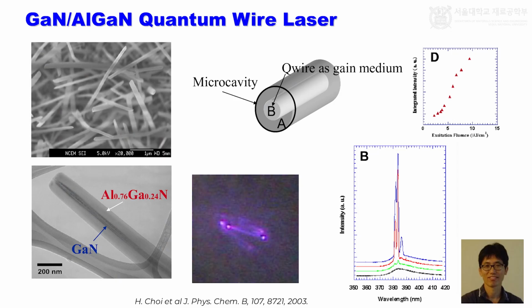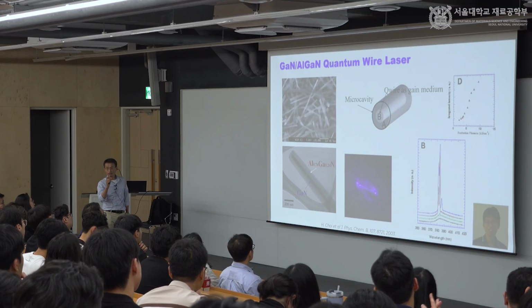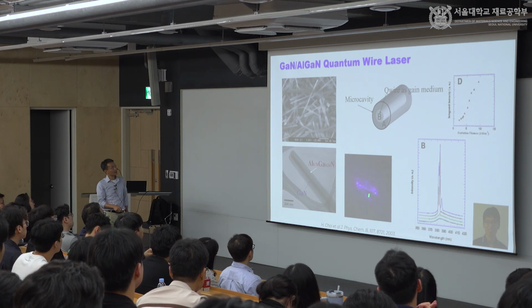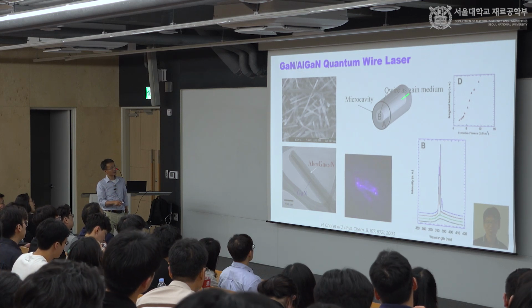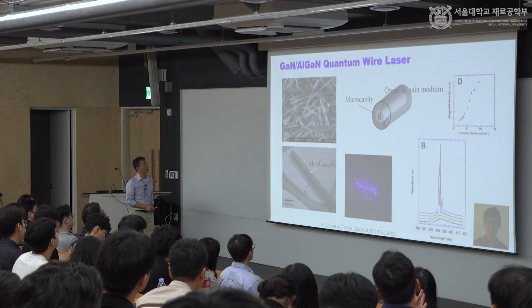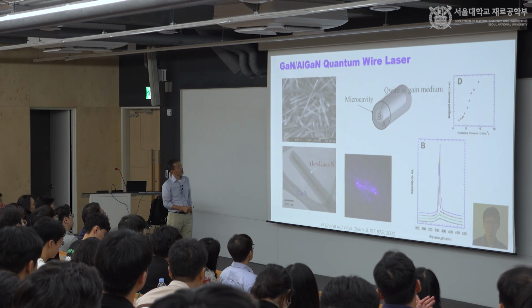And here, as I said earlier, is a core-shell nanostructure. It's gallium nitride, only about 10 nanometers thick, a highly confined quantum wire with a dielectric cladding of aluminum gallium nitride. That serves as a laser as well. This is a quantum wire based, strongly confined system.